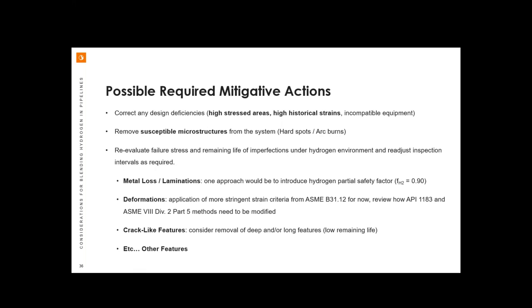Okay, so the possible required mitigative actions. We may have to correct any design deficiencies. We may have old facilities that have high stress areas. Perhaps we've had a high degree of cold bending or differential settlement or some other natural process over time that has caused high stress in our system. We may have incompatible equipment we need to look at. Of course, there are certain things that we may need to pay close attention to, like susceptible microstructures, particularly for vintage pipes. There have been documented failures related to hydrogen-induced cracking for vintage pipes, and there's no real assessment technique for that other than to essentially remove those susceptible microstructures from the system.